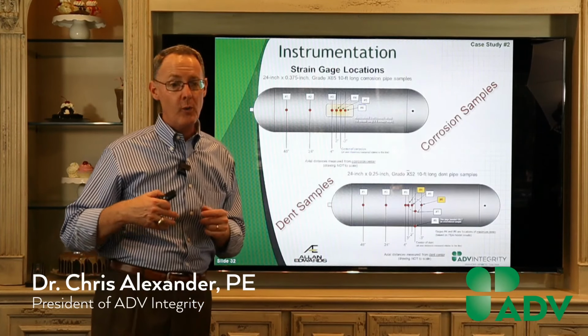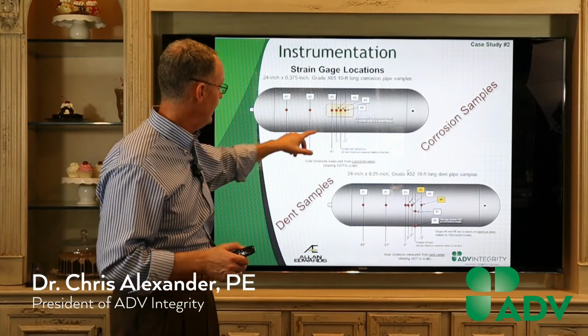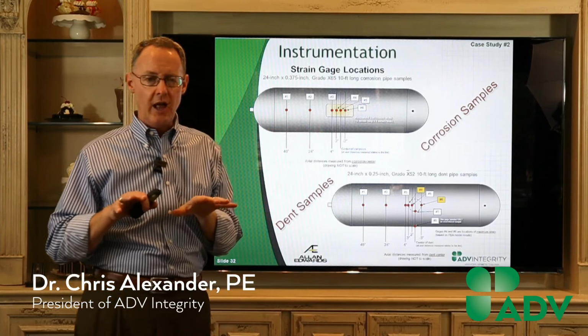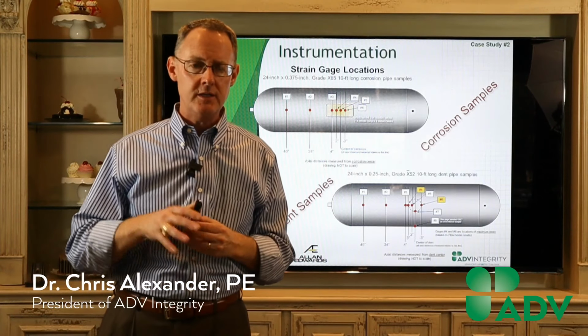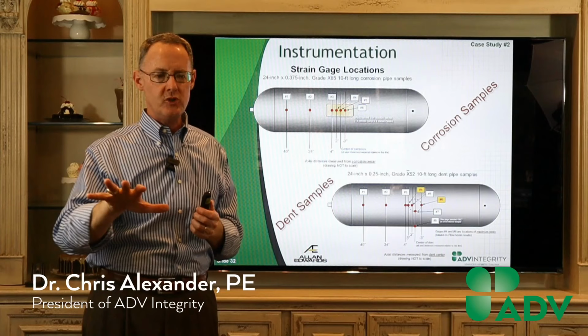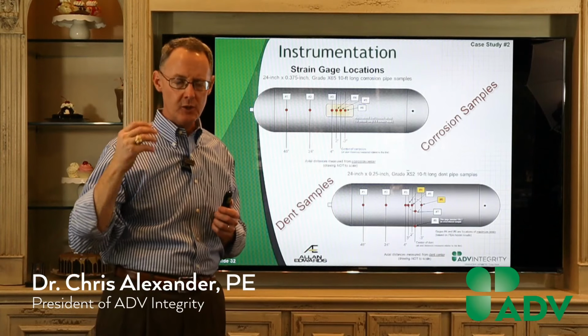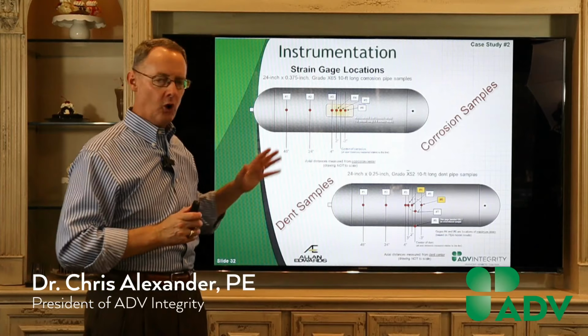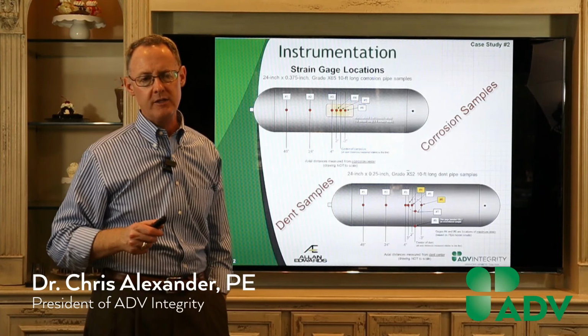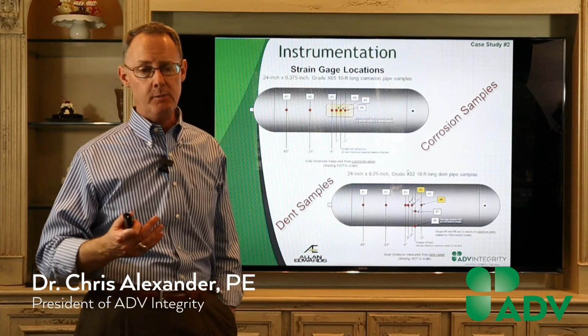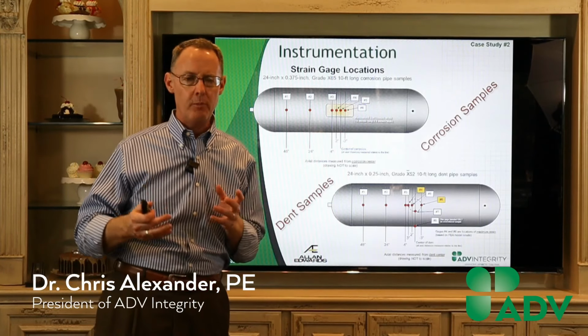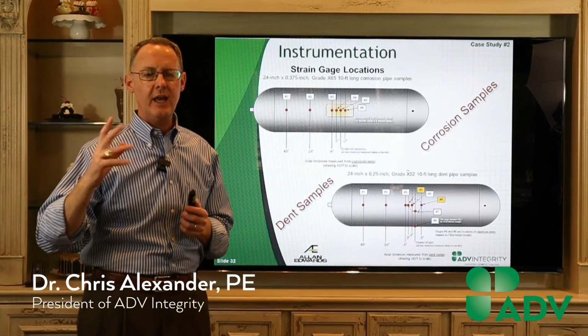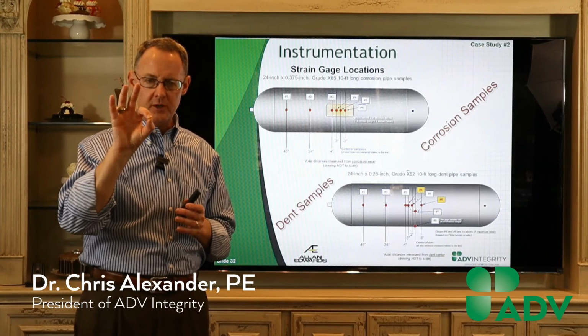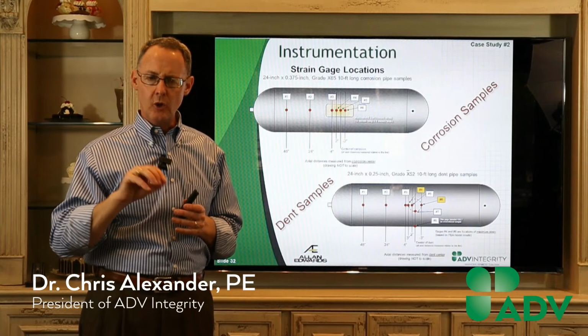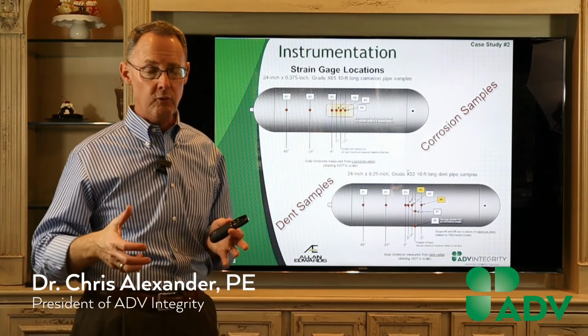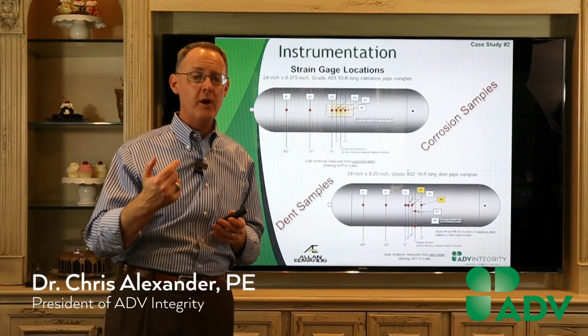As I alluded to earlier, we had a lot of strain gauges, and we're putting strain gauges in the feature on the base pipe. One of the challenges when you put a steel sleeve or even a composite is, how do I get that information from under the sleeve to outside the sleeve? So we always have wires running out. In the early days when we started doing this work on composites, there was a question from some of the composite manufacturers who said, is this going to affect our performance? We ran a lot of tests, and we really convinced ourselves that these little bitty small wires coming out from strain gauges don't have a significant effect on the structural reinforcement. Now, if we're doing leak repair, you better believe that would have an effect.